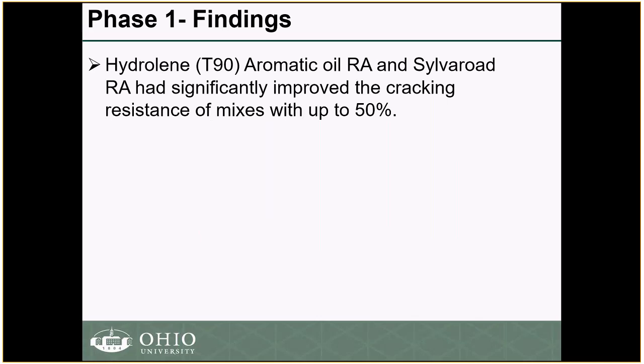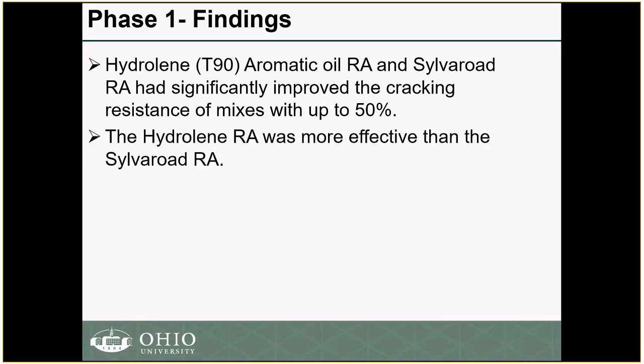So the findings from phase 1 are that using a softer binder was not able to overcome the effect of the RAP when we're using more than 30% RAP, and therefore we had to use a recycling agent, the aromatic oil, and the Sylvaroad RA that we have used.